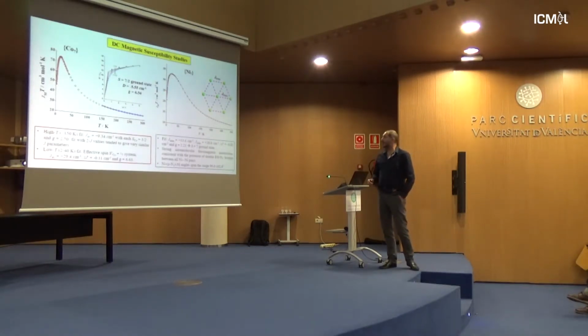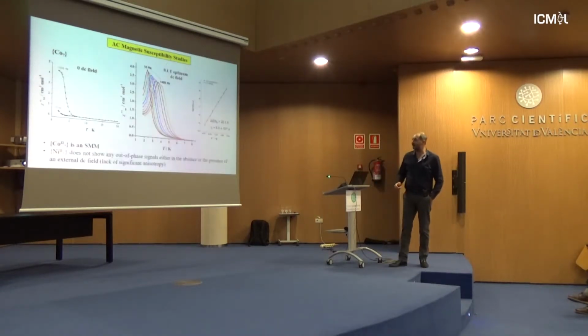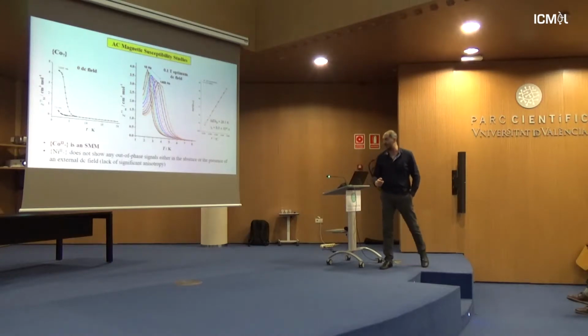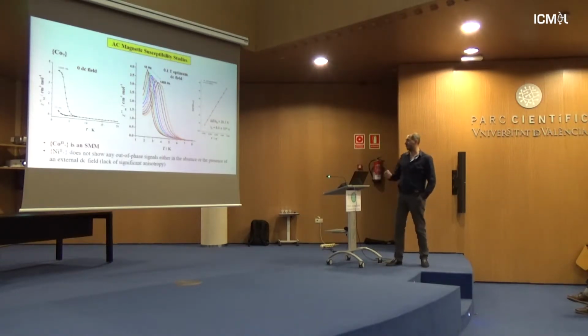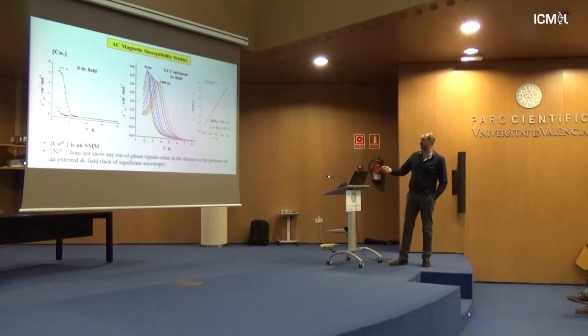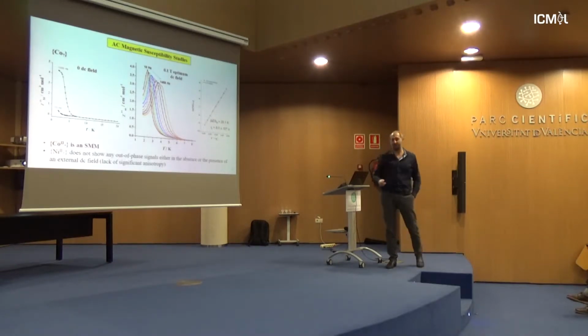Very small angles. So the magnetization data were also collected, from which we were able to determine a large negative D value. So for the case of cobalt-7, we have also SMM behavior, as we can see from this frequency dependence of the AC signals at low temperature, both in the absence and in the presence of a magnetic field. For the nickel-7, we were not actually lucky to have SMM properties at this stage. Now, because of this AC maxima here, we can construct a conventional Arrhenius plot, we fit the data to the thermally assisted region, and we get a barrier for the magnetization reversal, or relaxation, of around 28 Kelvin, with relaxation times within the 10 to the minus 8 second region.